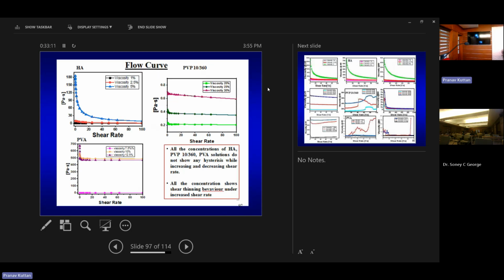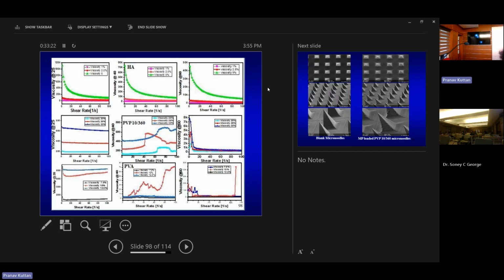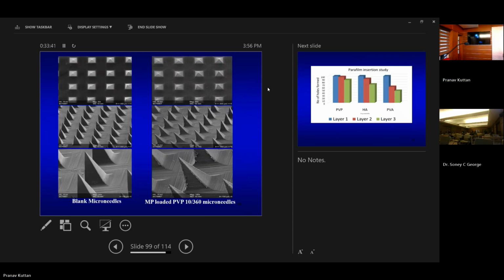Then the flow curve was also drawn. All the concentrations don't show any hysteresis, so this could be easily used. All the concentrations show shear thinning behavior. And this is the temperature dependent study. So we wanted to check the curing temperature and we optimized that. At 25 also it is fine, 40 also it is fine, but by 60 the curing has started, the viscosity started increasing. So we optimized 40 degrees Celsius for curing.